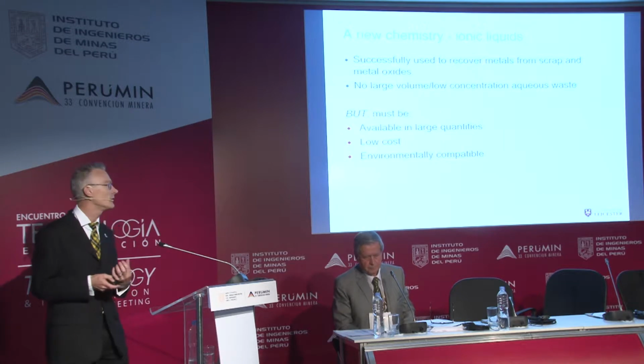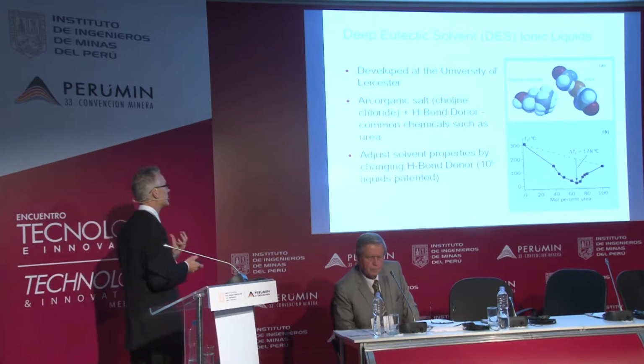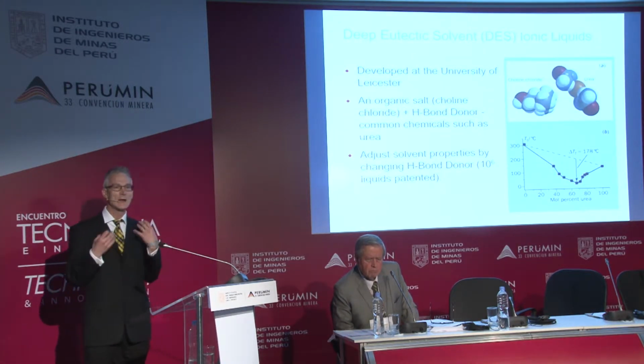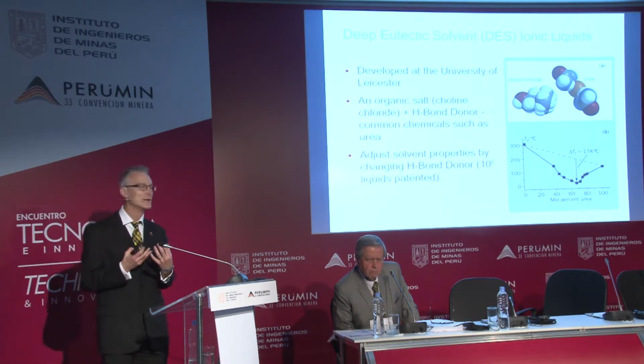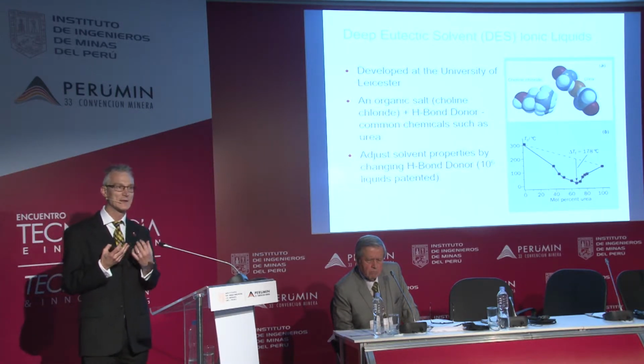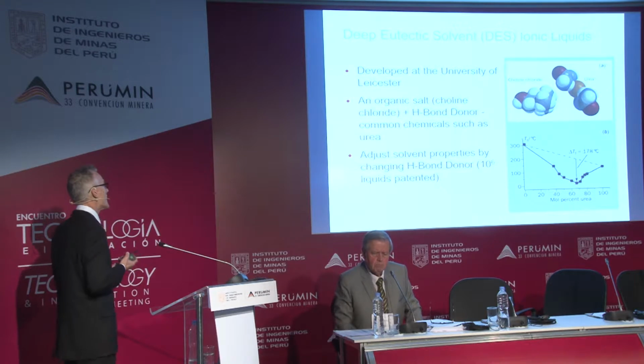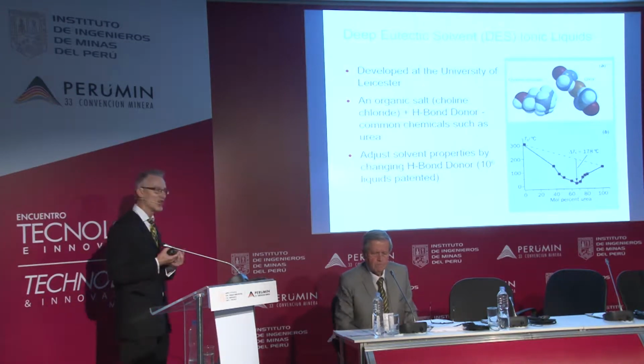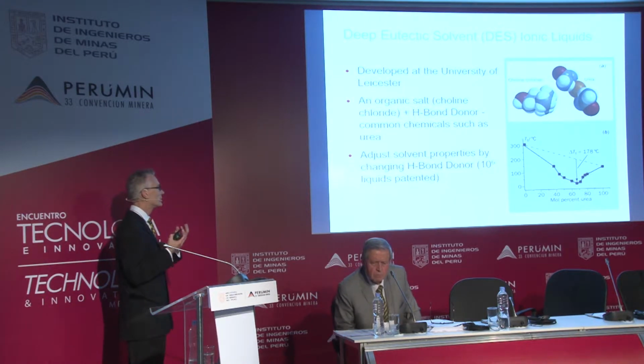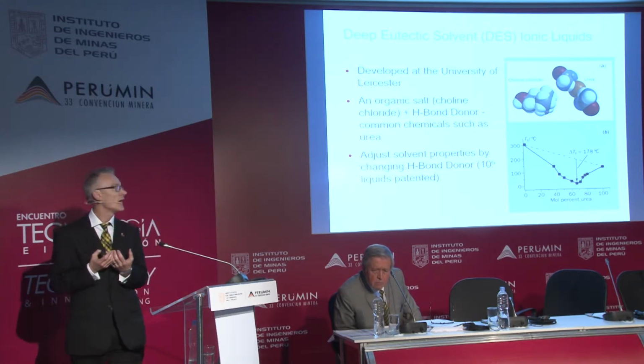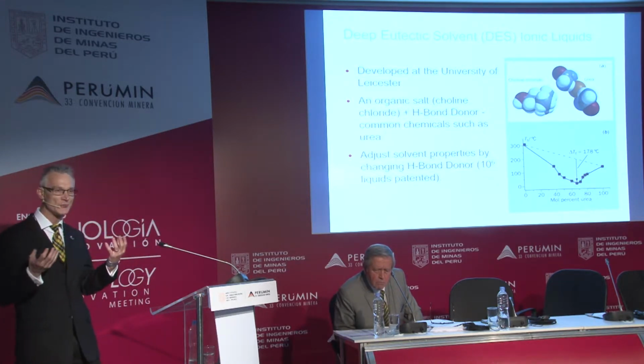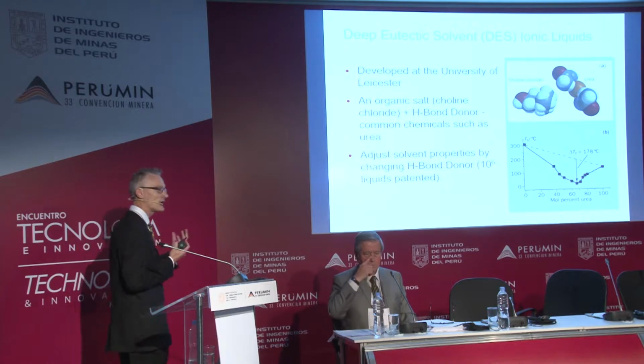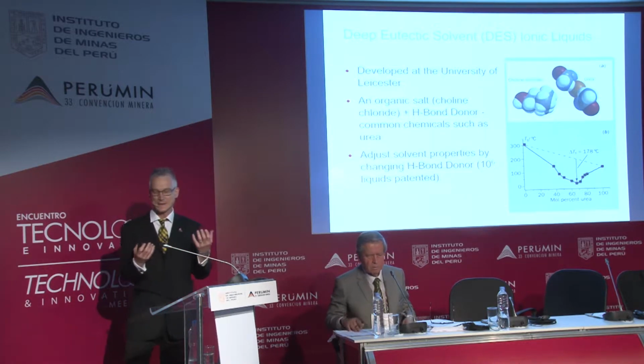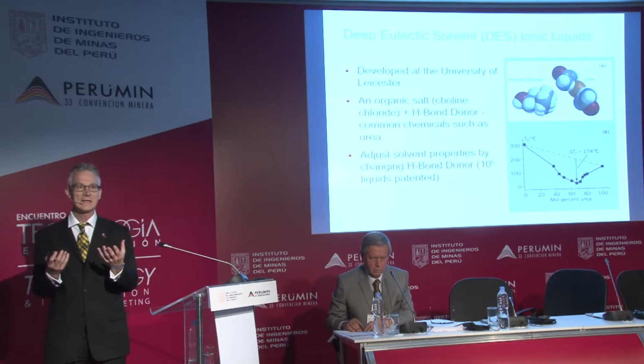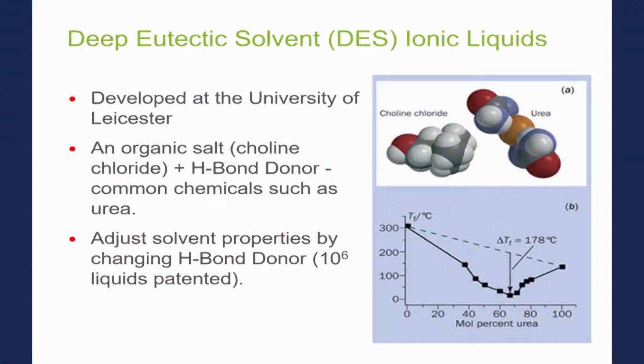Okay, but the real breakthrough here is what our chemists discovered at Leicester, where they developed a new class of ionic liquids called deep eutectic solvents. This is a mixture of an organic salt, choline chloride, and a hydrogen bond donor, so common chemicals such as citric acid, such as ethylene glycol, such as urea.